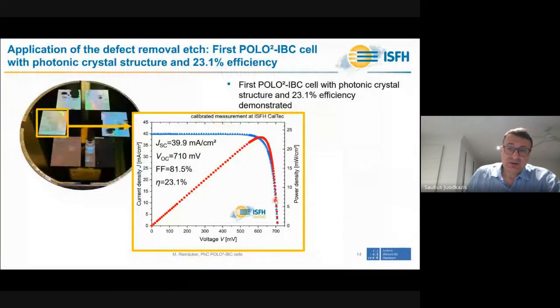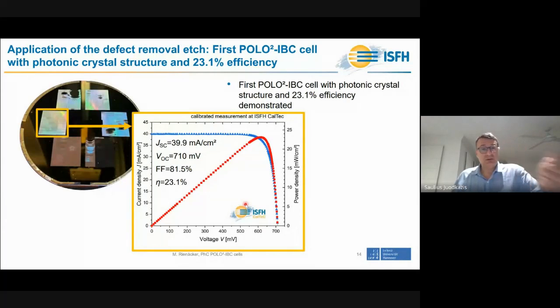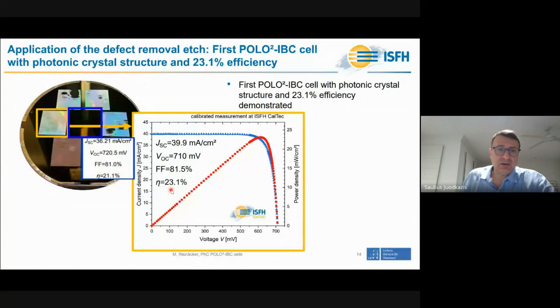And this is the result which was verified in Germany, and then verified at Caltech by independent measurement of the solar cell. So this was from this part of the pattern. And we obtained 23% efficiency when the neighboring solar cell here without light trapping performs at 21. So this was a very encouraging first result that light trapping with the periodic structure is really working nicely.